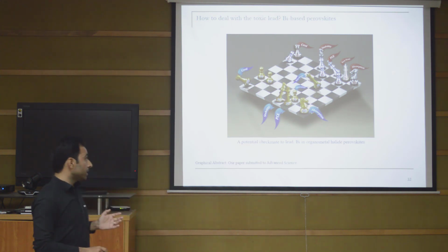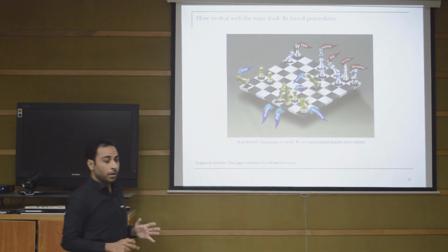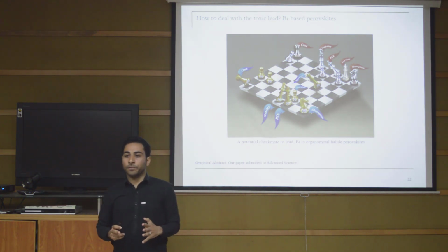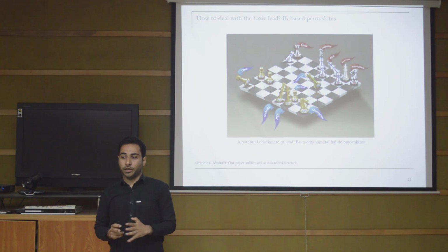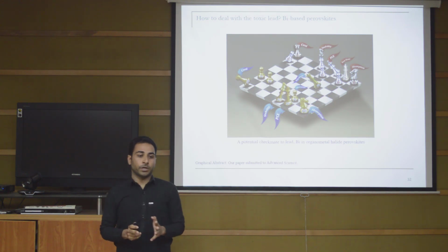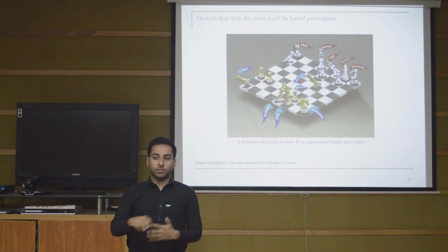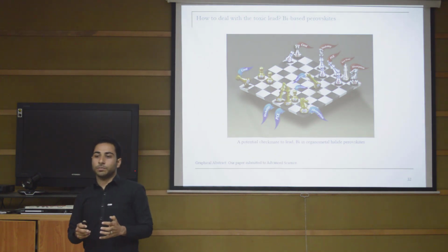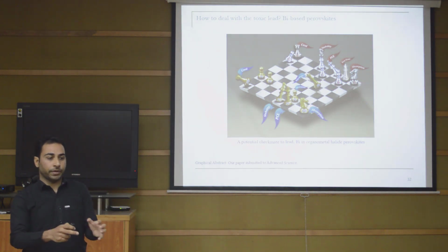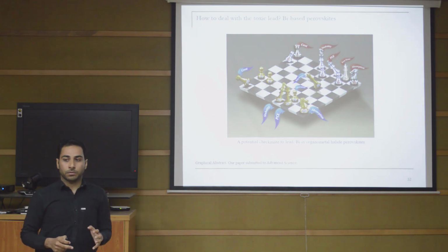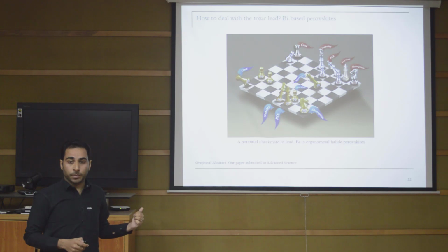And the main reason is, there are several reasons, but one of the reasons is the bad film morphology of the bismuth-based perovskite. When we are fabricating the bismuth-based perovskite, it is highly volatile as compared to the lead-based perovskite. So during the spin coating, the crystallization process is so quick that separate phases are formed, and one is unable to obtain a high quality bismuth-based film.